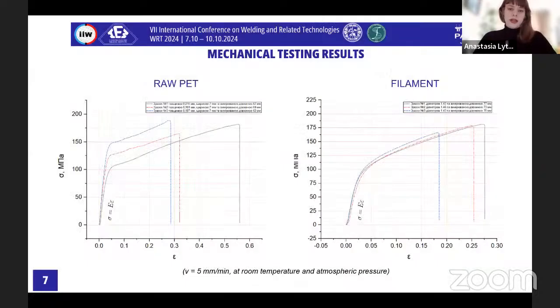So the next step in my research was testing the mechanical characteristics of both the bottle with raw plastic and the filament after extrusion, and comparing their properties. We can compare parameters such as stress and strain at breaking points and yield points, because this allows us to analyze the material's endurance and resistance to physical loads in the future. The experiment was tested on a Shimadzu AGS-X 10 kilonewton tensile machine, and I conducted 3 experiments on the PET tape and 3 on the filament.